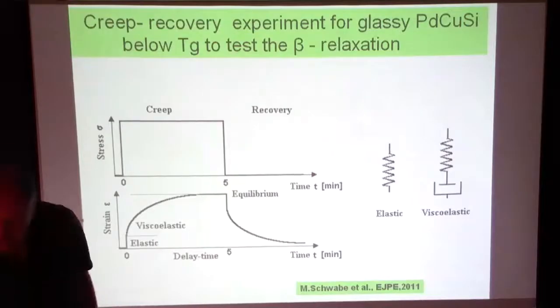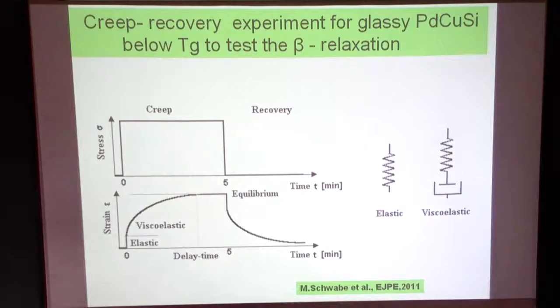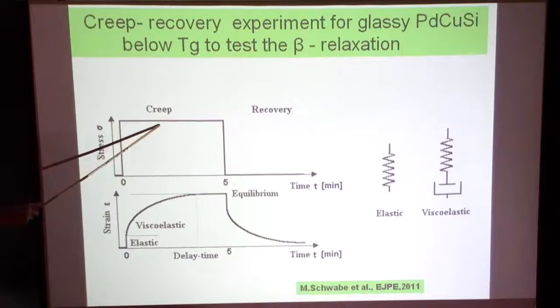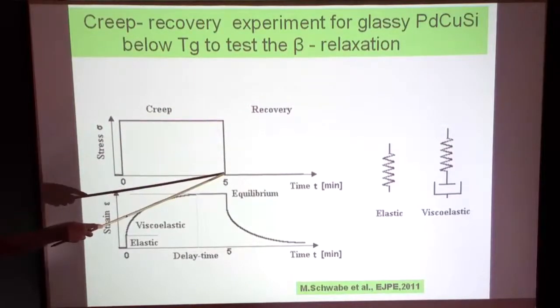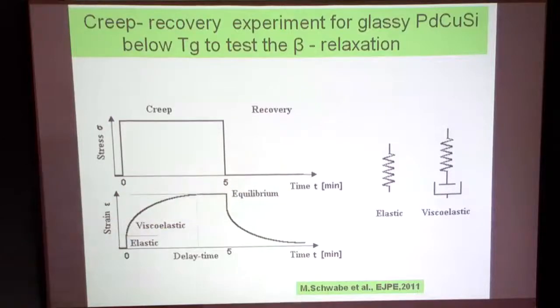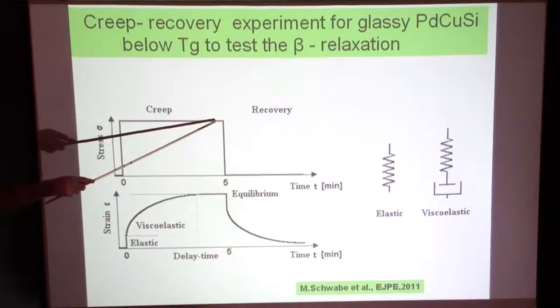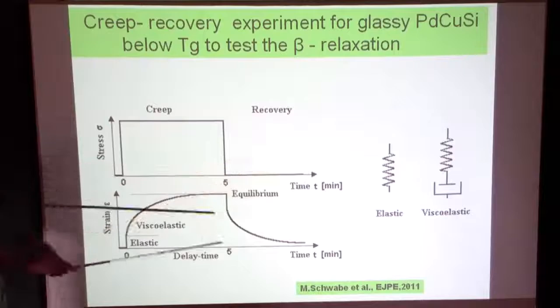Okay. I want to make one more point for the experimentalists here. As I made in the beginning for stress and strain-driven systems, now we have somehow mechanical versus thermal noise. We had a long discussions here from our friends here, the Jean-Louis Barrat group. If you do a creep measurement, and we'll do a creep measurement in the future, is actually show you that we apply suddenly a certain stress, wait for a certain time, come down again to stress 0 and wait for the recovery. So one system is just as mechanically activated, more or less, and at one point you just wait until the system relaxes by temperature.